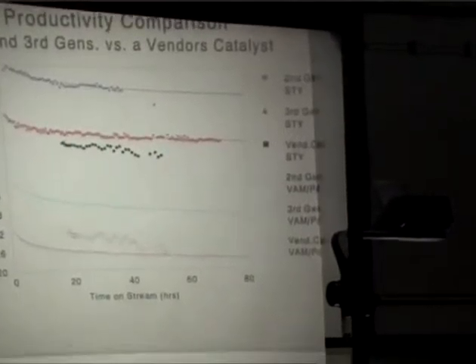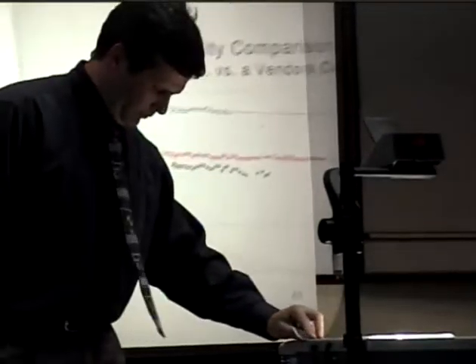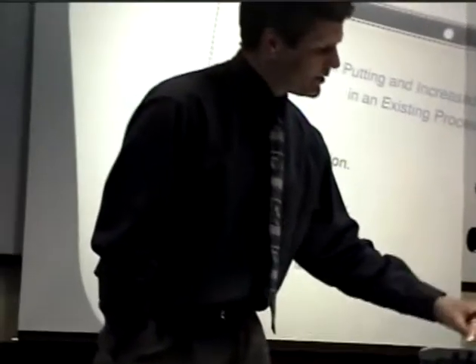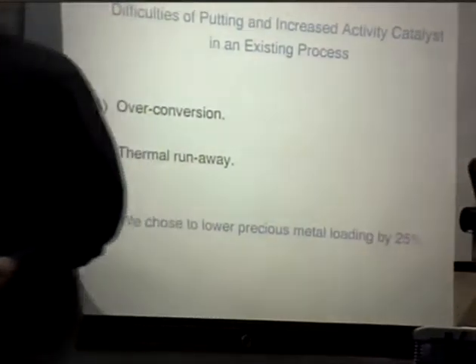And what we learned is, even with our second generation catalyst, now in red, that the vendor's catalyst couldn't pack that much activity per volume of reactor. But our problem was right here, is that they were using palladium much more efficiently than we were. But then with this third generation, this improvement, we see that we do use that palladium much more efficiently. The problem comes in terms of how do you apply this.